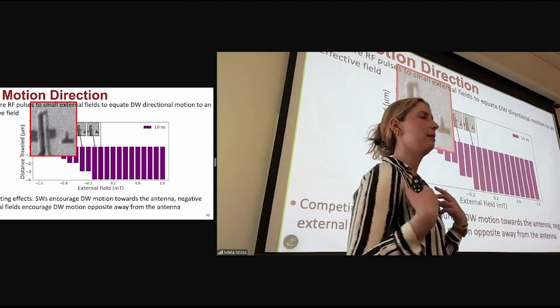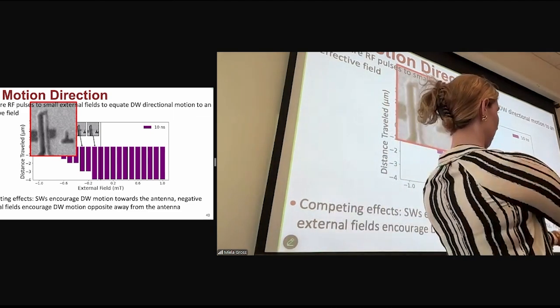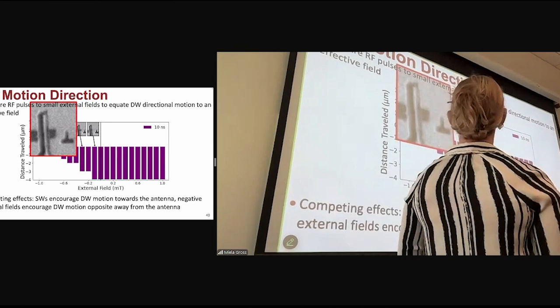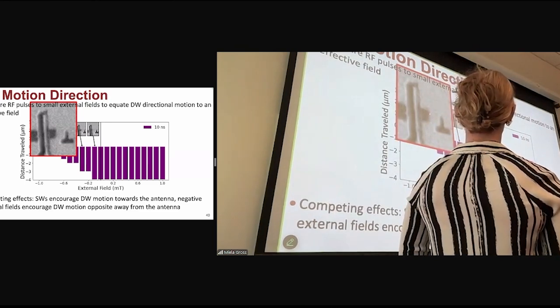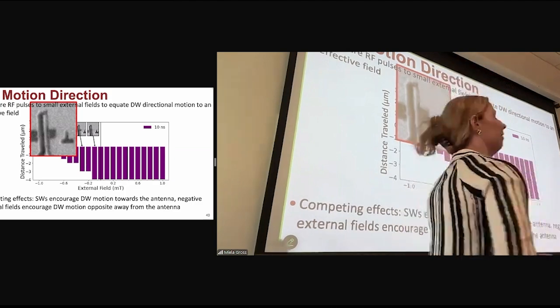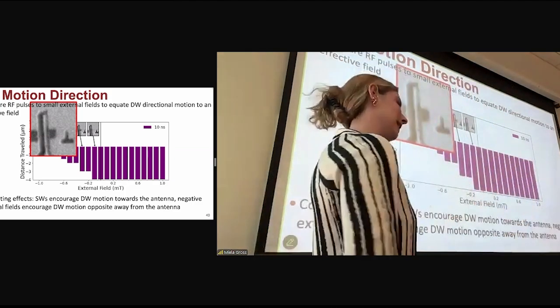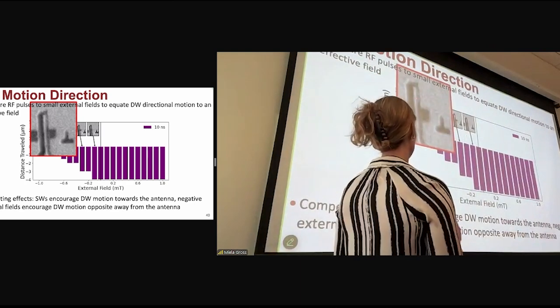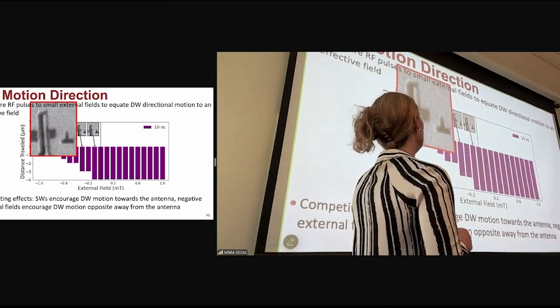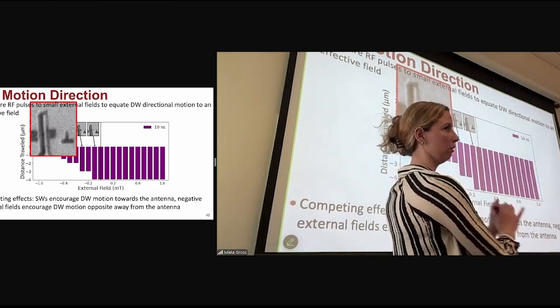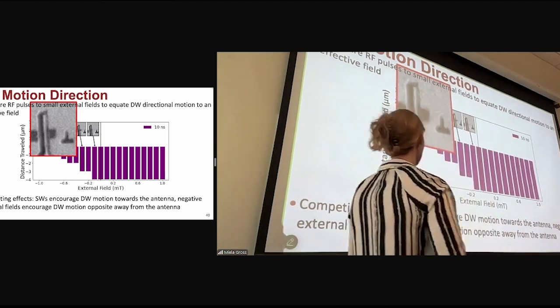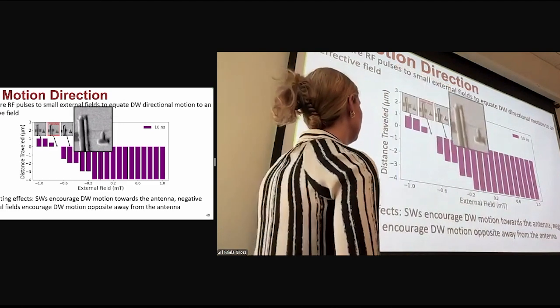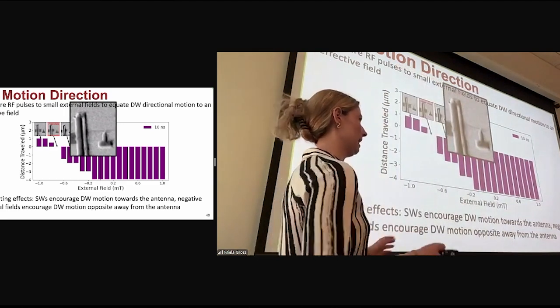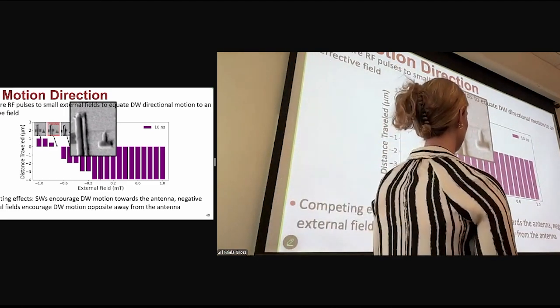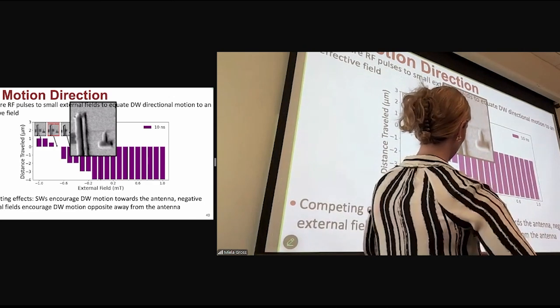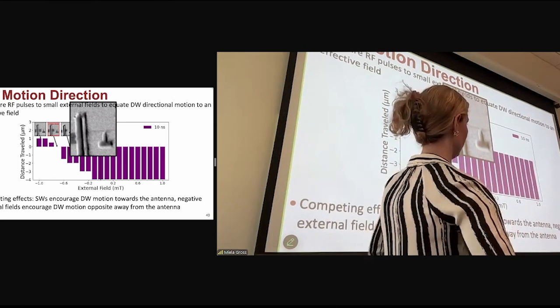As I've shown in the past, spin waves like to propagate domain walls towards the injector source. So the spin waves are going to encourage the domain wall to go under the injector antenna. However, if we apply small negative magnetic fields, it's going to encourage the expansion of this down state, which is going to propel the domain wall to the right, so away from the injector antenna. So as we first start off, we don't apply any external field, and we see, lo and behold, the spin waves completely pull that domain wall under the injector antenna.